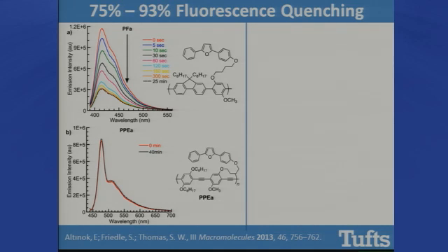When we make the donor fluorophore, or the electron donating fluorophore, a smaller band gap material, we decrease the energy of that excited state electron. Even though the furan undergoes a reaction with singlet oxygen, an analogous reaction as we see up here, and we can confirm that with both UV and NMR evidence, we see no response in terms of fluorescence, which means that the energy of the excited state is a really important consideration when talking about electron transfer here.